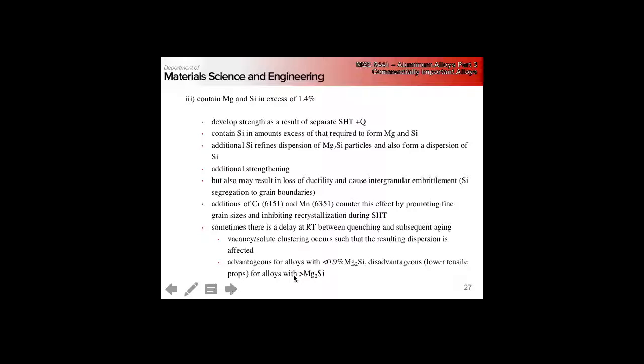There's often an unusual heat treatment associated with these—basically a quench and then a hold at room temperature for a while before the aging step. The idea is you can get some clustering, vacancy and solute clustering, so that we modify the dispersion of secondary phase particles, because things tend to nucleate where these clusters are. Doing this is very dependent on composition: if we're under 0.9% magnesium-silicon with a slight excess of silicon, it's good; if we're higher than that with an excess of silicon, it's not.